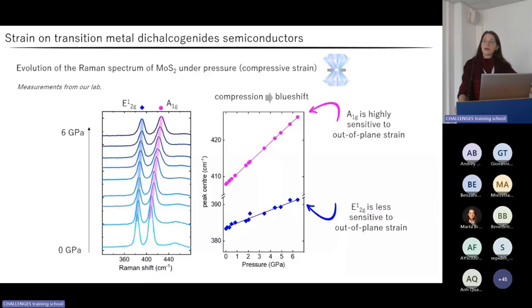When we consider high-pressure measurements, on the other hand, the situation is somehow reversed. Here you can see some high-pressure Raman spectra collected in our laboratory on molybdenum disulfide. In this case, both A1G and E1-2G peaks blueshift due to the application of a compressive strain. However, as you may notice, the variation in frequency of the A1G mode is much larger compared with the variation in frequency of the in-plane E1-2G mode, because, as we have discussed before, the application of pressure on two-dimensional materials mostly results in a compressive out-of-plane strain.